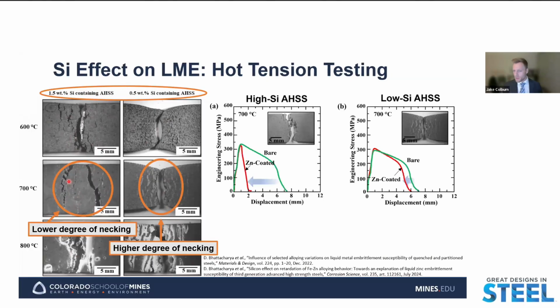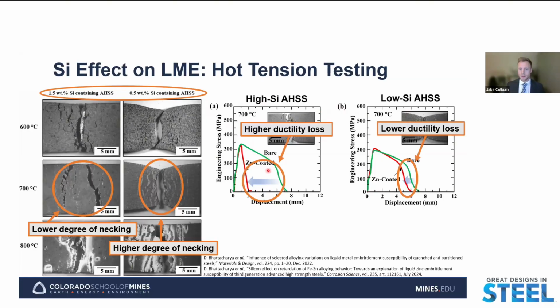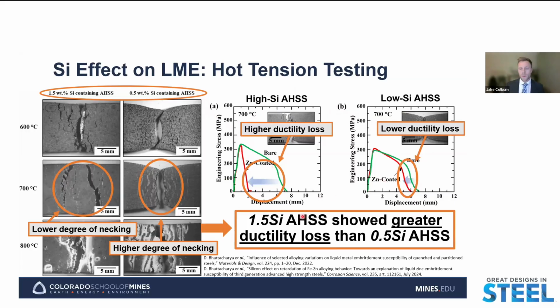We can also do a more quantitative look at the ductility loss when the sample is compared in its bare state versus its coated state, again testing at a temperature of 700 degrees C. What we see is that there is a greater ductility loss between the bare and zinc-coated steel for the high silicon containing steel as compared to the lower silicon containing steel at 700 degrees C. Overall, we can say that this 1.5 silicon advanced high strength steel showed a greater ductility loss, a greater degree of embrittlement, than the lower silicon containing steel.